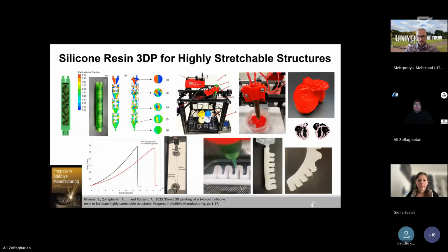Also, we work on silicone. One of the very interesting materials in soft robotics is silicone, because it has quite high elasticity, and it can be mixed with other materials that have different amounts of rigidity. So we use two-part elastomer silicone, EcoFlex A and B. One of the issues in 3D printing of silicone is the mixing of these two parts. We came up with a design of a static mixer that is not commercially available, in order to mix the two parts A and B.